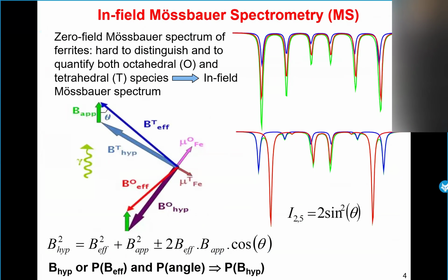In this domain, Mössbauer spectrometry is a very powerful local probe technique, especially in-field Mössbauer spectrometry, as presented by Jean-Marc previously. By applying an external field, we can split the two subspectra and have quantitative information about each iron site. From this we obtain information about the hyperfine field, but also about the spin structure from the spin canting. And for more complex structures, we need to find the appropriate correlation between the effective field and the spin canting in order to obtain the distribution of the hyperfine field.